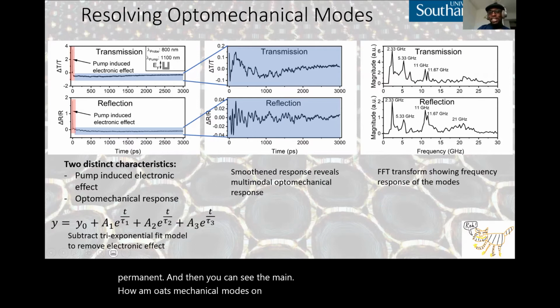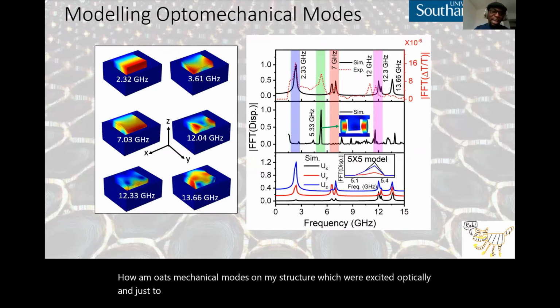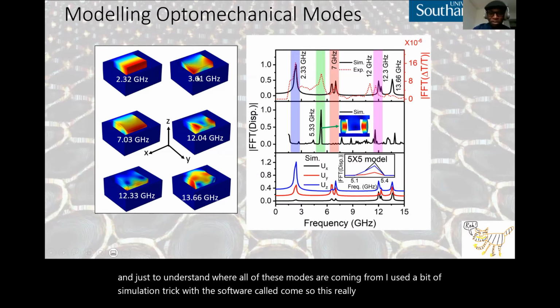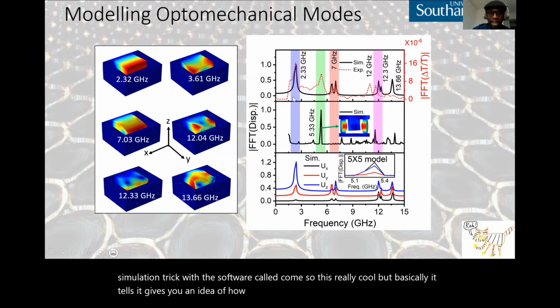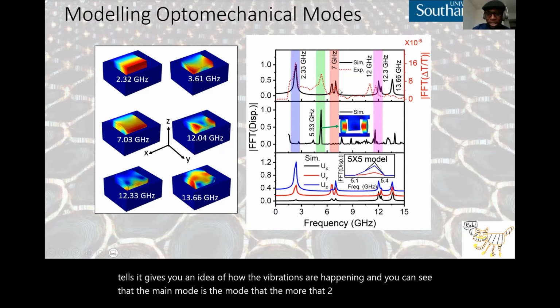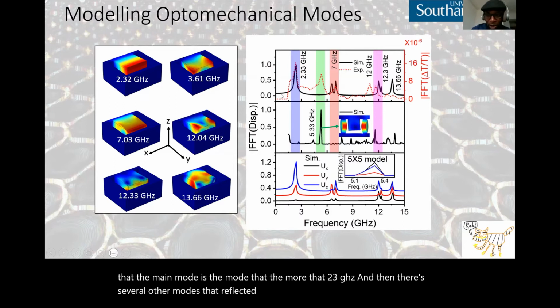And just to understand where all of these modes are coming from, I used a bit of simulation trick with a software called COMSOL. It's really cool, but basically it gives you an idea of how the vibrations are happening. And you can see that the main mode is the mode at 2.3 gigahertz, and then there's several other modes that are reflected as well. I have superimposed the simulation frequency response, which is the black line, on the experimental response, which is the red line, the red curve that you can see.